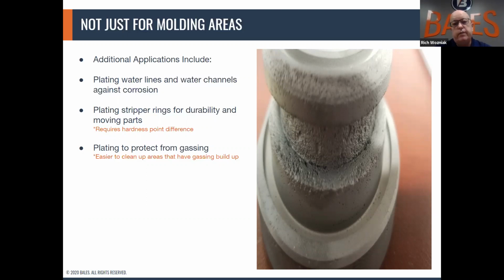As you see here, it's kind of a funky picture. However, you see the corrosion that occurred. This is one of our customers whose tool was only in service for less than 6 months, and the water just destroyed it. So we put an Electroless Nickel coating on there, cleaned it as well as we could, and protected it until they were able to build some new cores. Then we coated Electroless Nickel on those water channels.